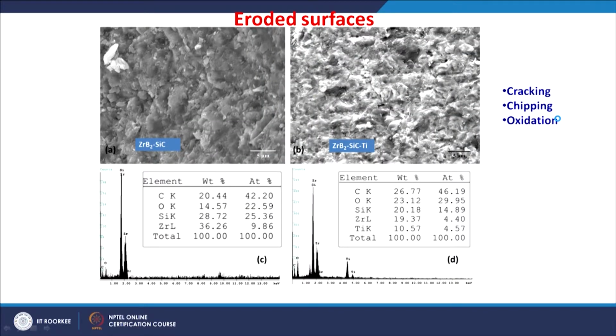So, let us understand the mechanisms of material removal in the given erosion conditions. You see in the zirconium diboride silicon carbide, there is a lot of chipping and then cracking. EDS analysis also indicates oxidation. When titanium was added, we can still see the chipping and cracking, and the surface becomes more rough, which indicates more cracking. More cracking, chipping and oxidation are also observed in the eroded material of zirconium diboride, silicon carbide and titanium. So, overall the material is removed by cracking, chipping and oxidation for these two composite materials.